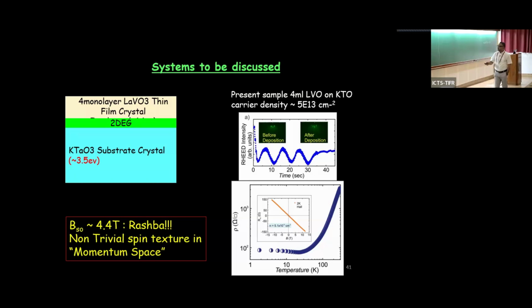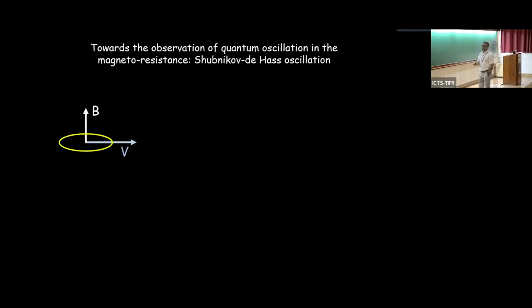And you can see that this material is conducting in nature, the interface is conducting in nature. The Hall is completely linear with a charge carrier density around 5 × 10^13 per centimeter square. And we calculated it has a very strong spin-orbit coupling, and the Rashba strength is around 4.4 Tesla, which is the strongest possible reported for any oxide material.